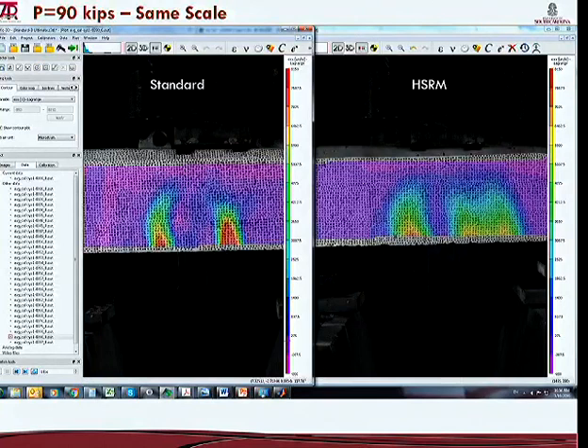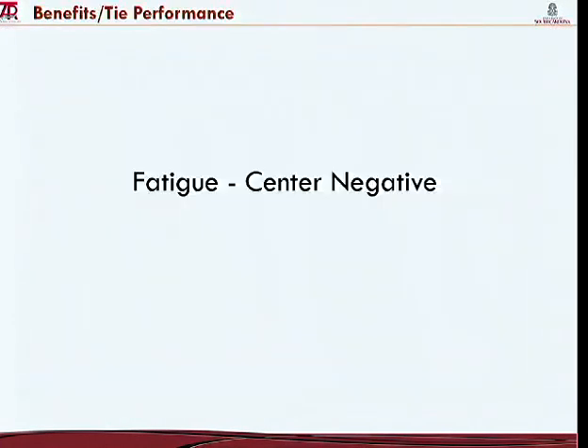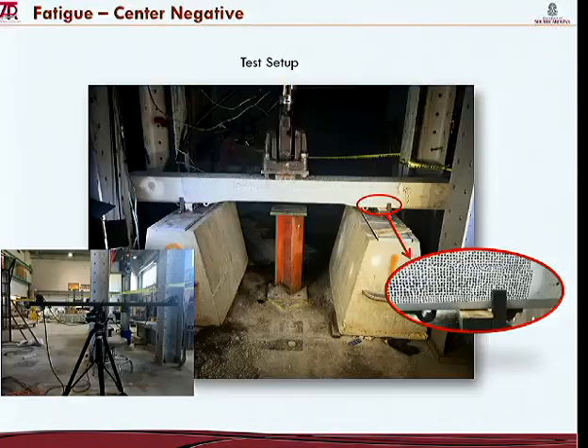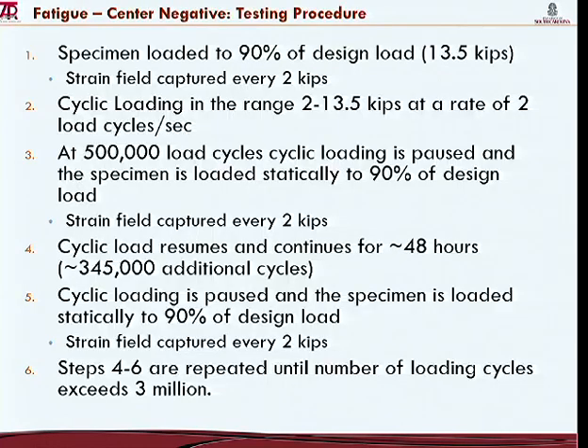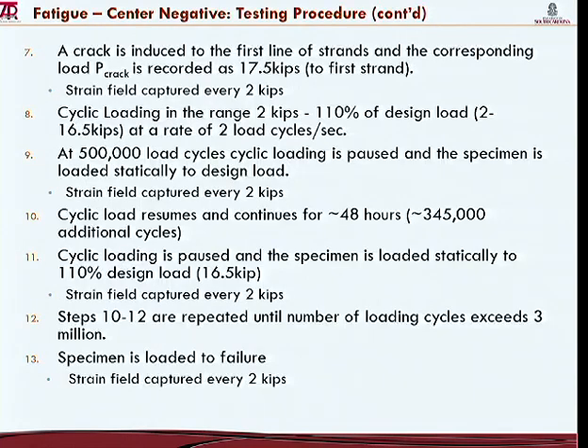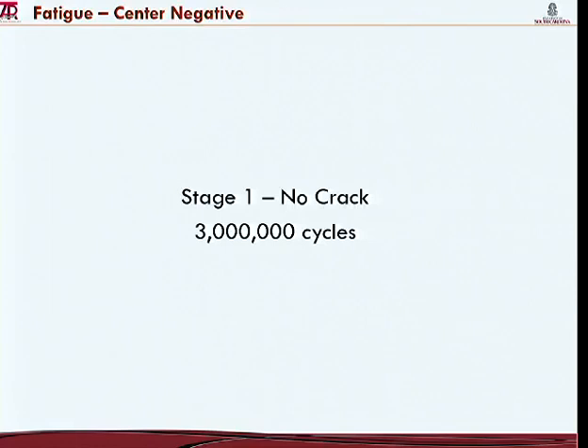All right. Then we tested the specimen in fatigue. There was no established procedure for this, so we did 3 million cycles, loading to 90% of the design load, monitoring the strains. Then we induced a crack, loaded the specimen another 3 million cycles, and at the end we loaded the specimen to failure. So stage 1, no crack, 3 million cycles.